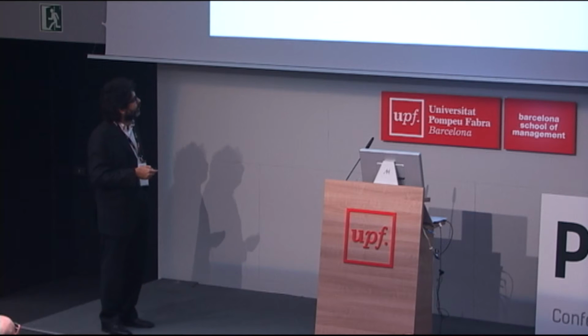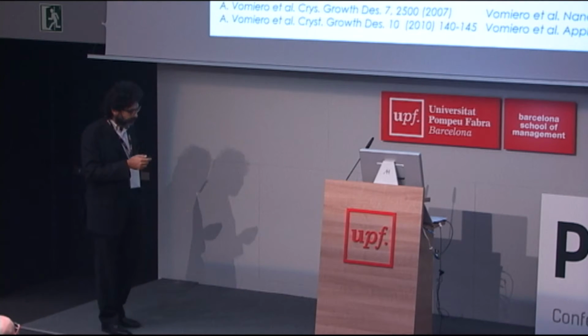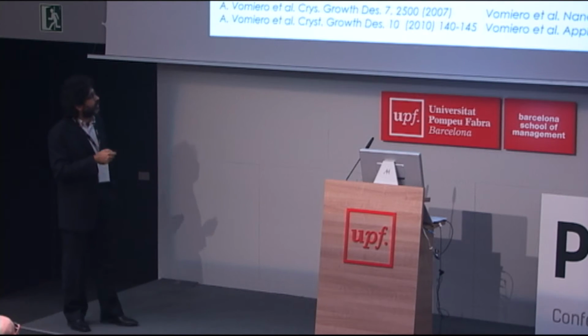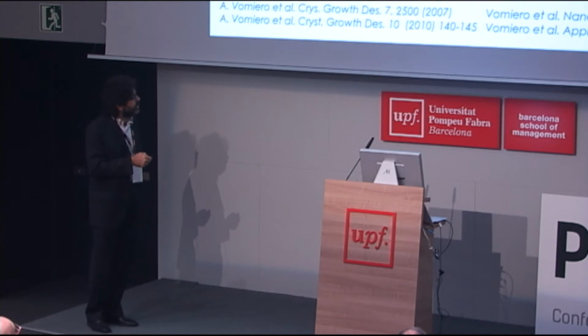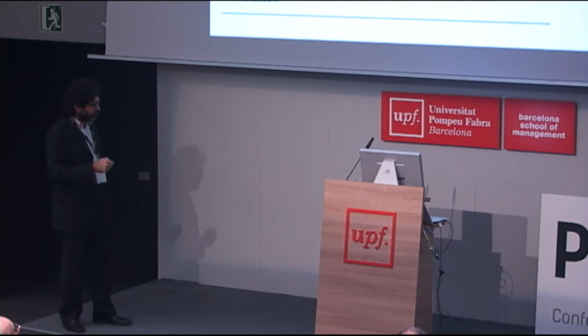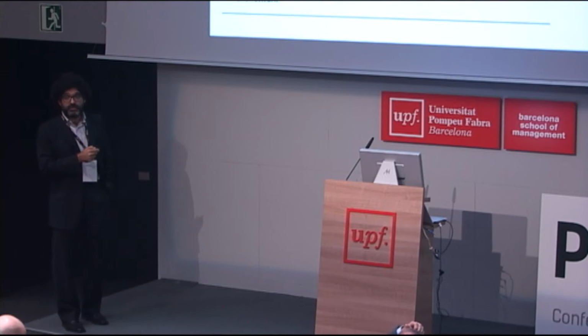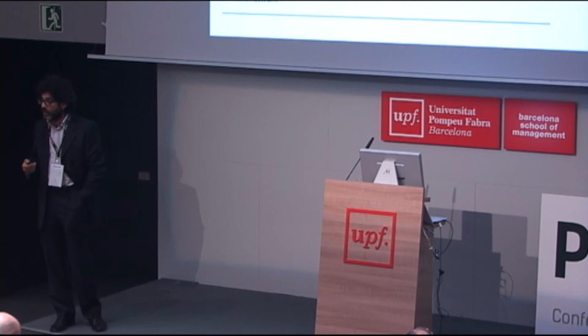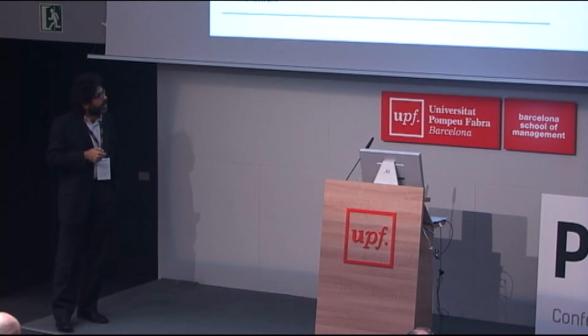So what we tried to do is grow our nanowires in different geometries and shapes. We can control the size and length of nanowires. And then we wanted to test nanowires compared to a standard mesoporous system, or a system composed of nanowires and nanoparticles. In this respect, you can have the high specific surface of nanoparticles and very good electronic collection given by zinc oxide nanowires.